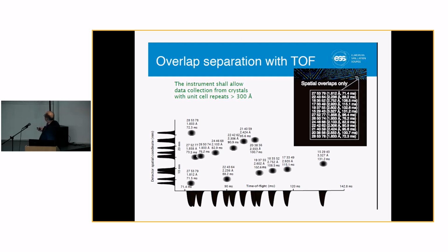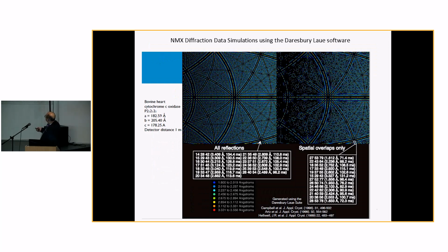And we can see that the time of arrival of this diffraction spot is 73.3 milliseconds, and the one here is 3 milliseconds later. So you can actually see both in space and time where the diffraction spots are appearing and when they will arrive because of the nature of the spallation neutron source. From the measurement physics point of view, we have the ideal situation of minimizing the background noise underneath the signal reflection intensity. So this is a very powerful tool that has been developed in Lund for this sort of very large protein unit cell.